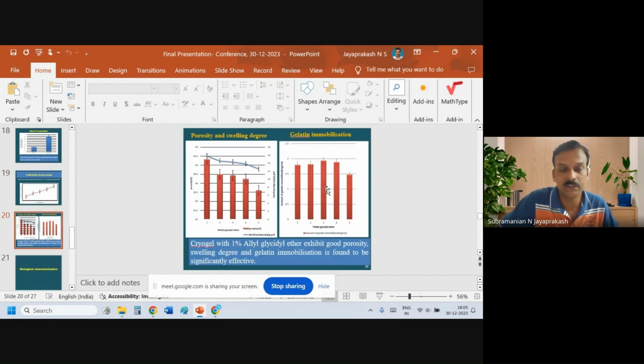So this slide concludes the porosity and swelling degree and gelatin immobilization optimization study. With the optimized condition, we found that cryogel with 1% allyl glycidyl ether exhibited good porosity and swelling degree, and gelatin immobilization is found to be significantly effective.